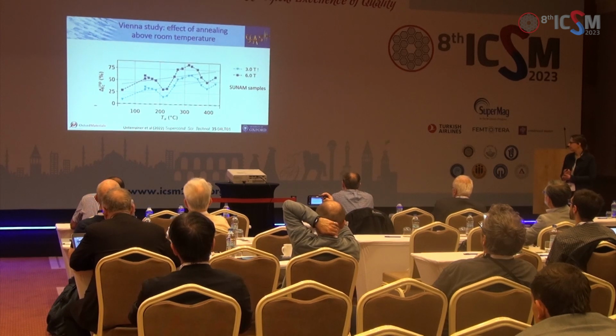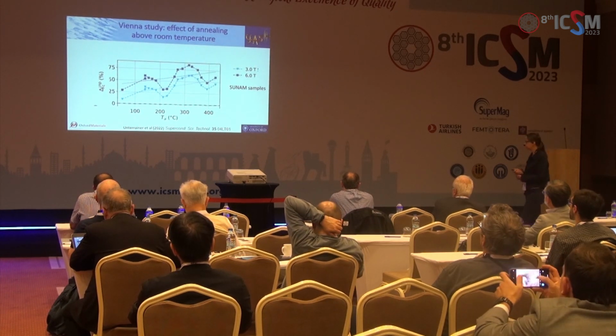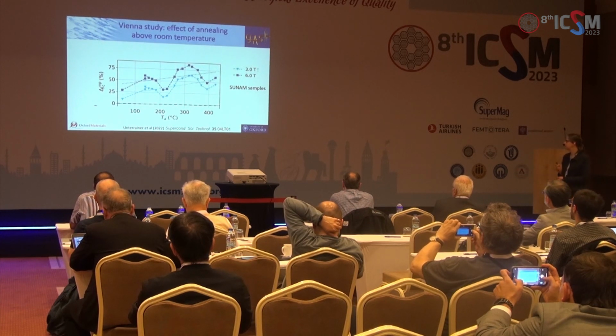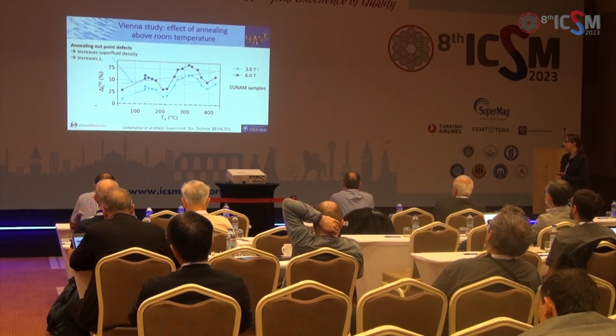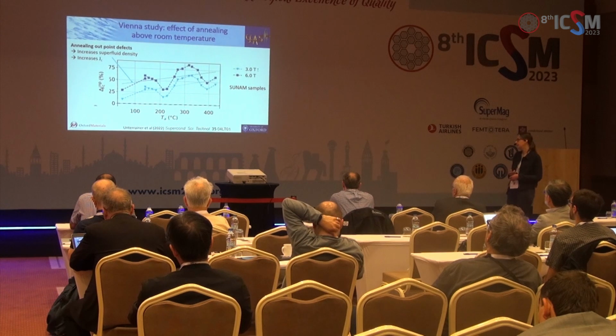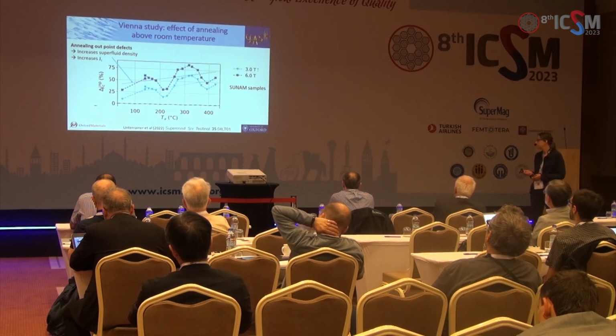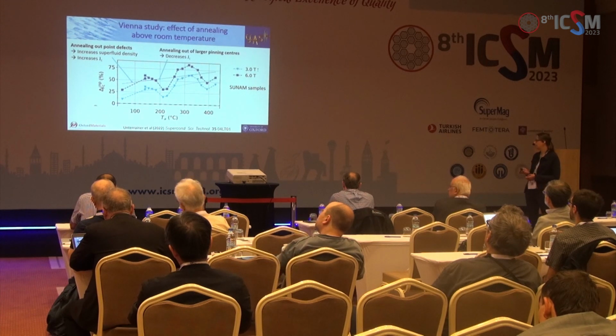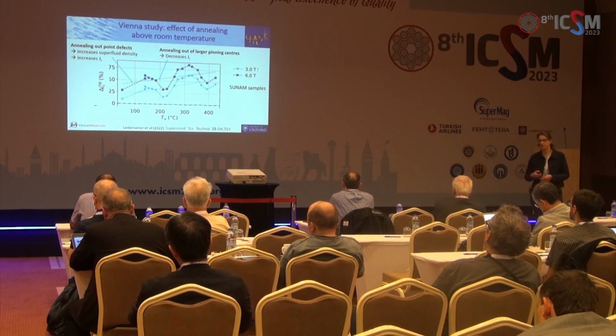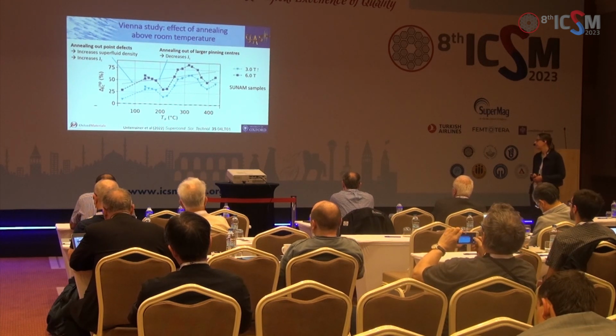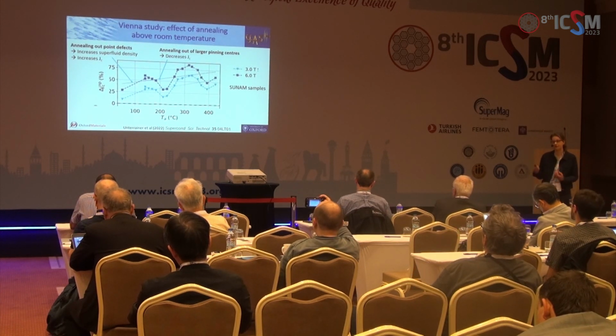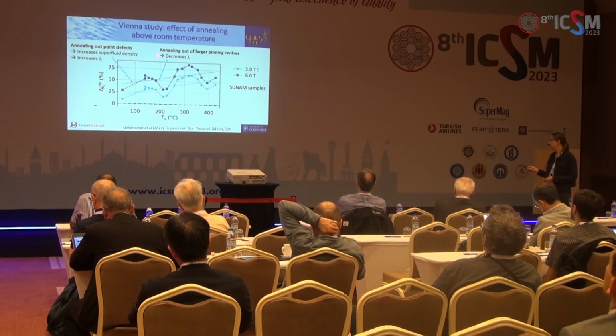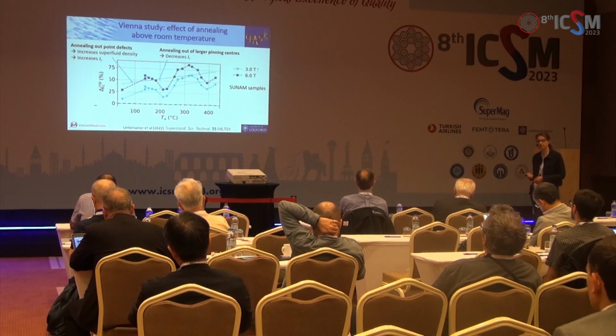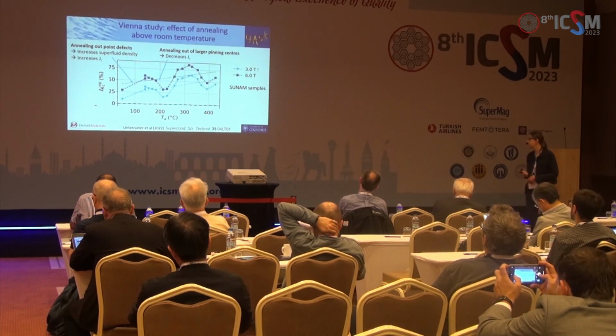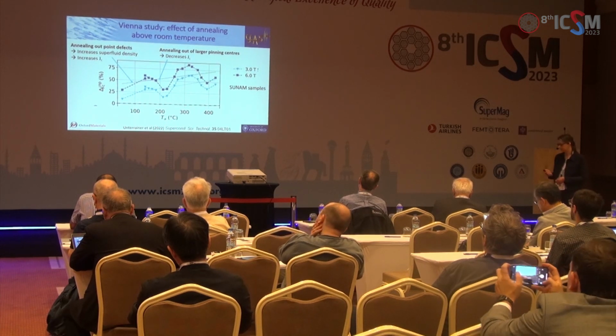What happens to JC? Well, this is a rather complicated diagram, and I'm not sure that I've got the explanation right, but I think what's going on is that we get this initial increase in JC when we do the annealing, because we're annealing out point defects, which is increasing TC, and will increase JC as a result. When we get a bit higher in temperature, we might be annealing out some of these larger pinning centres, some of these defects that we put in that are larger. And if we do that, then we're reducing flux pinning and JC will go down again. There's another peak here. I'm wondering if this is to do with defects that have higher activation energies, for example, which can then be affected at higher annealing temperatures.